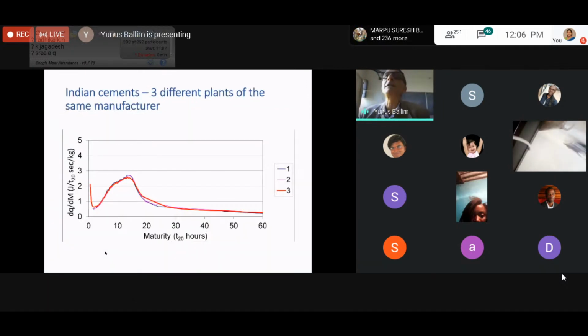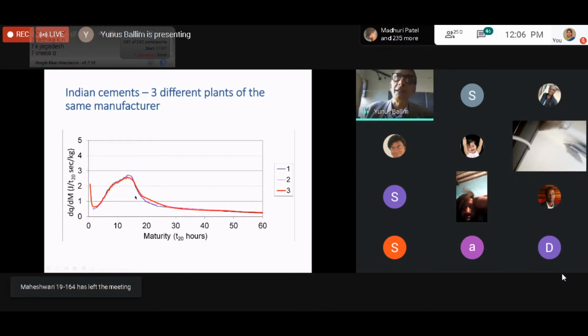Here's an example of 3 cements from a manufacturer in India. It happens to be the same manufacturer, but from 3 different plants. What is interesting here is that this manufacturer is actually producing quite consistent cements. What I also wanted to show you is this lower peak heat rate than what you saw with the South African values. And that, I think, is as a result of the preponderance of the dicalcium silicates rather than tricalcium silicates.